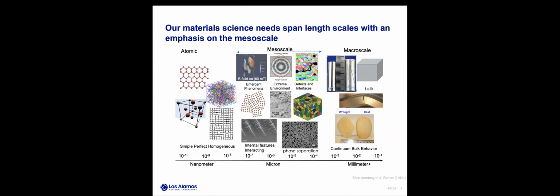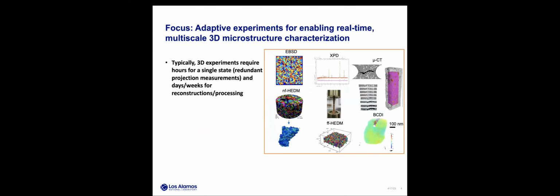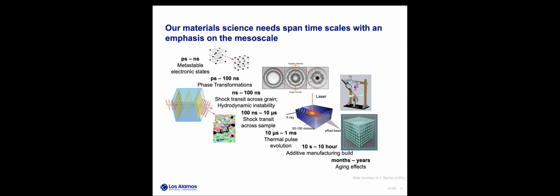And through the knowledge that we've gained over the past several decades, we now understand that the behavior within this mesoscale regime plays a significant role controlling and influencing macroscale properties. So in addition to characterizing the features in the mesoscale regime, we also want to observe the materials dynamics across a broad range of timescales, going all the way from nanoseconds to tens of seconds, and in some cases even hours, months, and years. This allows us to examine phenomena such as phase transitions, phase stability, kinetics of all these things happening, damage nucleation, and all the way up to solidification and microstructure development during manufacturing and aging.